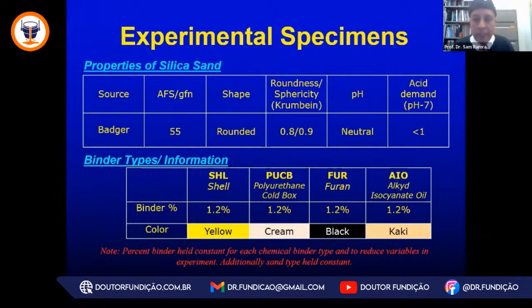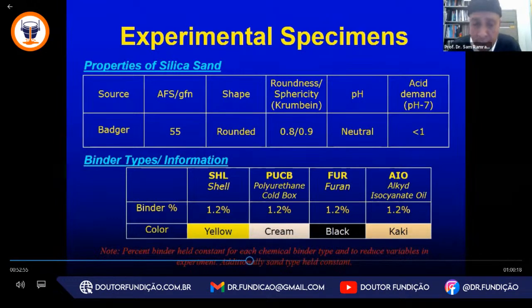So we did a simple experiment where I will show you the longitudinal or axial displacement for a silica sand. This is a round grain silica sand that has a neutral pH, and onto that silica sand, we place four chemical binder systems. One is a shell phenolic system, one is a polyurethane cold box system, another is a furan system, and another an alkyd isocyanate oil. All of the binders, we chose to put the same total amount of binder, and we kept the sand the same. And I put a note on the bottom. The percent binder is held constant for each chemical binder type to reduce the variability in the experiment.